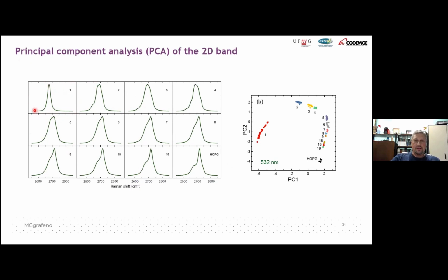that takes some mathematical approach to extract the main spectral components of these curves here. Our analysis showed that this band, what is seen here, can be very much mapped in a phase space that we call the two main principal components, PC1 and PC2, and they just project in some parts of this chart. So 1 layer projects here, 2 layers project here, 3 layers, 4 layers, 5, and these are the standard samples that we have. All right, so we built this standard PCA phase space.